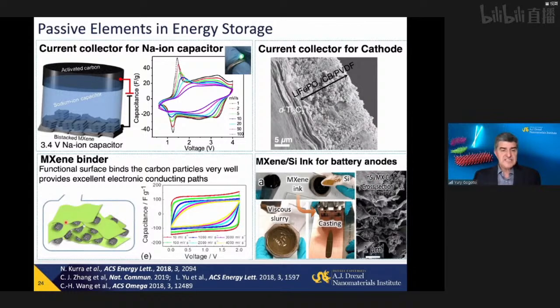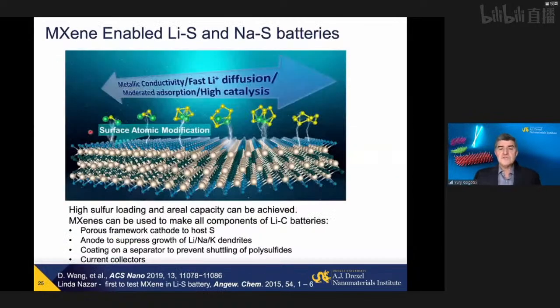And you can use them actually instead of polymer, even for activated carbon in electrochemical capacitors to accelerate and improve charge storage here. And of course, these applications start finding use in many different systems, for example, in lithium and sodium sulfur batteries, where MXenes can be used as host for sulfur. They strongly adsorb polysulfides. Linda Nazar was the first one to show this behavior, and many other groups, including our group, followed up. They can adsorb polysulfide, they can catalyze transformation.